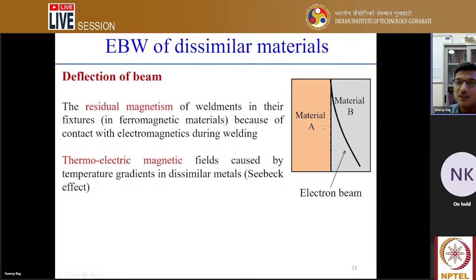But what happens when the two materials are different? Then residual magnetism actually creates a problem, and even there is a presence of the fixtures also. In that case, the thermoelectric magnetic field will try to deflect the electron beam towards one type of the material. That is because of the Seebeck effect. So because of the Seebeck effect, the deflection of the beam can happen towards one particular material. So that is the usual problem in case of the dissimilar welding of the electron beam welding process.